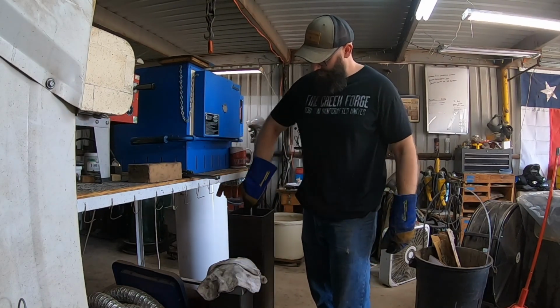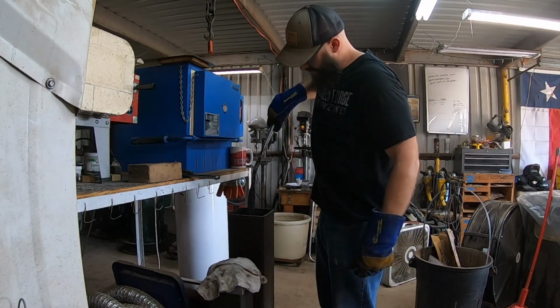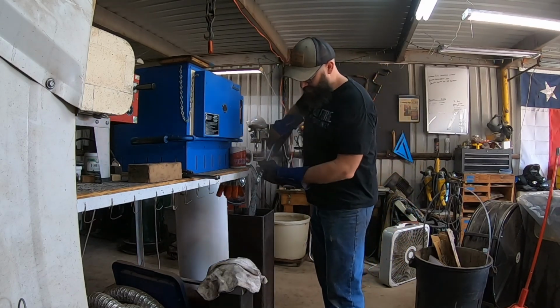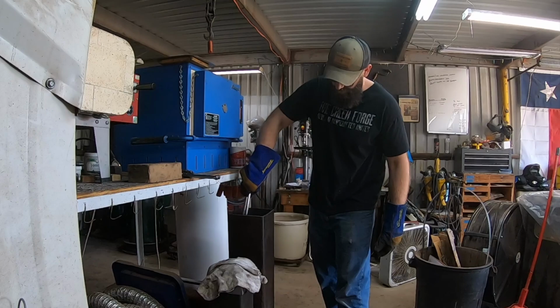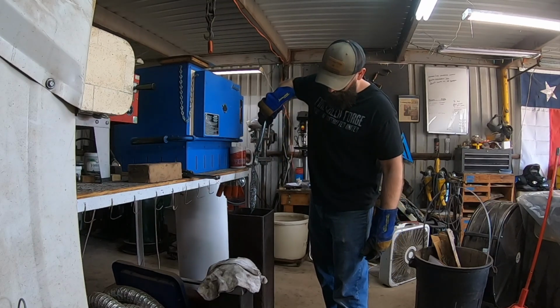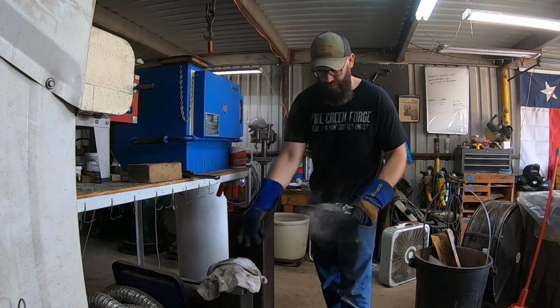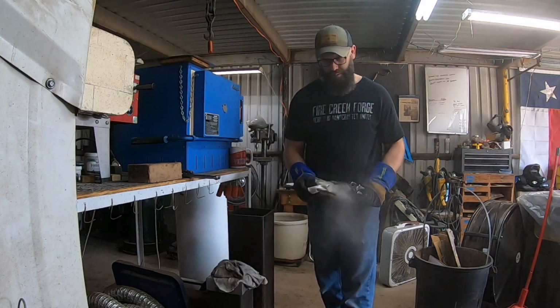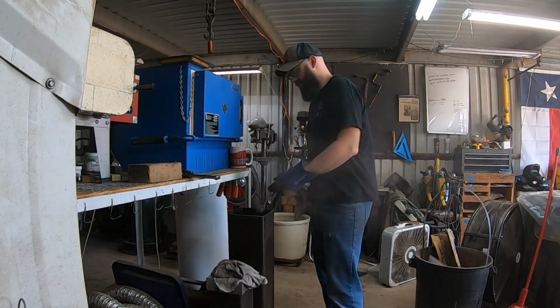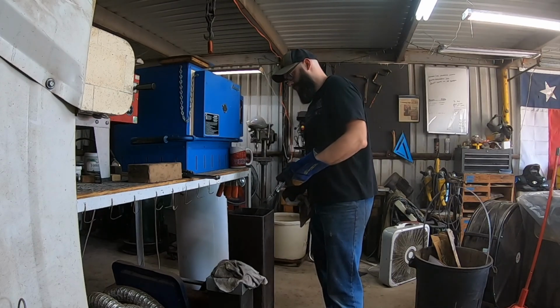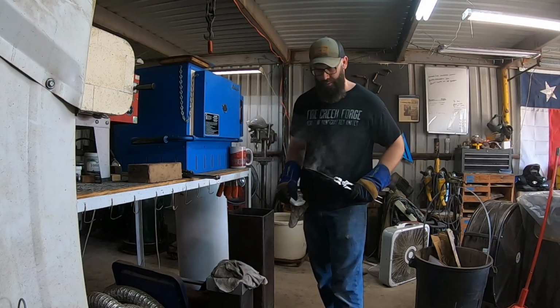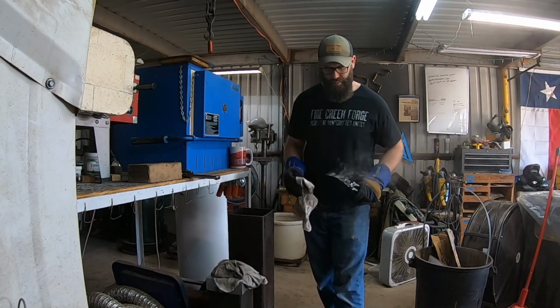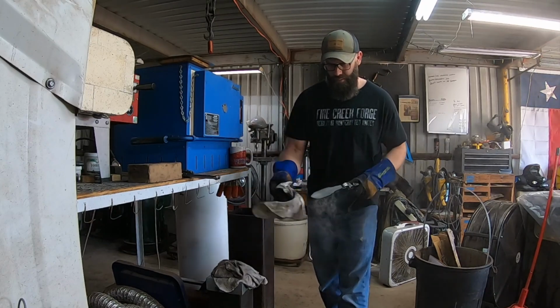I don't want to quench the blade all the way down to ambient temperature. This is a good way to end up with more warps and even cracks in your blade, and it's not necessary for full hardness on the steel. I'm looking for a specific temperature range in which the oil does not immediately evaporate off of the blade despite a little bit of smoke coming off of it.